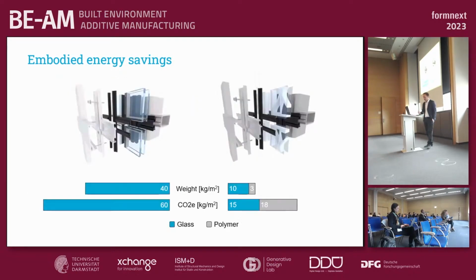And so our idea is basically to not only reduce the mass in the building, but also reduce the material from this energy-intensive glass. And so switching from the left side, the traditional IGU, to the right side, a composite panel with only 2 millimeters glass on each side. And there we can expect a lot of reduction in weight and CO2 emissions.